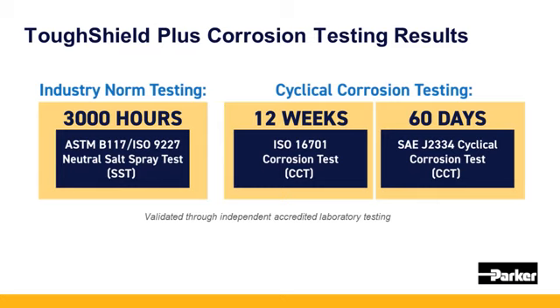But just how much better is Toughshield Plus? So it's starting off with zinc-nickel, proprietary, but what does that mean to me? Well, you're going to get 3,000 hours of salt spray resistance. So the industry norm is, again, static salt spray testing. SAE requires 144 hours, which is our primary governing body. Typical zinc in the industry is going to be 144 to 500 hours. Typical zinc-nickel is 500, maybe to 1,200 hours, but again, it's highly dependent and there are a lot of exceptions. And again, tested only to static salt spray testing. Toughshield Plus provides 3,000 hours of salt spray testing.